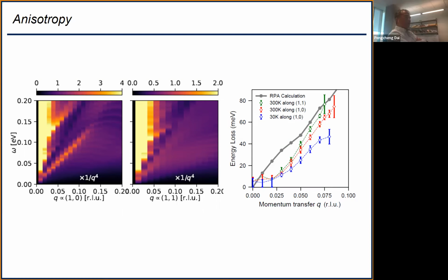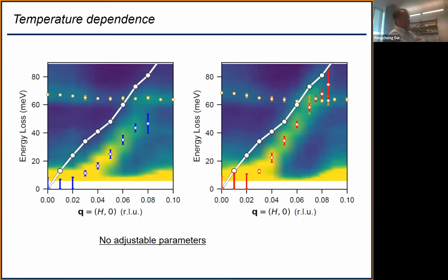Is there any other technique that can see this besides your technique? I know you have a unique instrument. The stuff you can do, very few other people can do. Can RIXS, for example, see this thing as well? RIXS, if they had good enough resolution, yeah, I think so. Modern RIXS, you can have a resolution of about 10 meV, right? I think the best I've seen is 30. I thought the one at Brookhaven was six. Yeah, 10, 15. The whole dispersion curve stops at 60. So conventional RIXS will be tough. RIXS instruments, for sure, the production instruments have 30 meV. Those are not good enough, so you'd have to do better than that. But I think in principle, RIXS should see it, and they have much better momentum resolution than we do. So I would think they would have no problem.